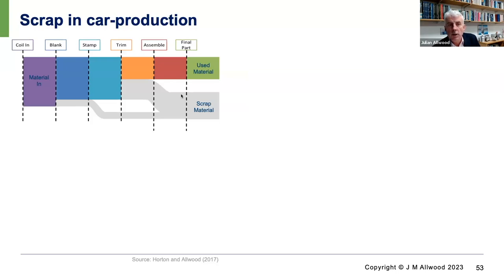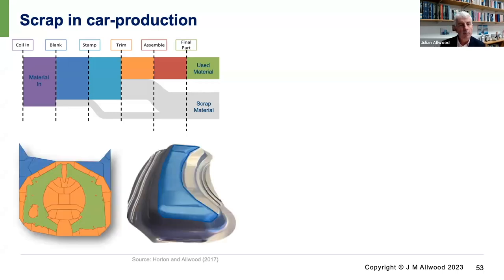Here's an analysis we did 10 years ago about making cars. When you make the body in white in a car from sheet metal, it turns out that on average, you scrap just about as much material as you use. In fact, the reason is not the blanking process, where you cut the orange blank out of the constant width coil of blue material, but it's the deep drawing process, which gives shape to the flat sheet metal.